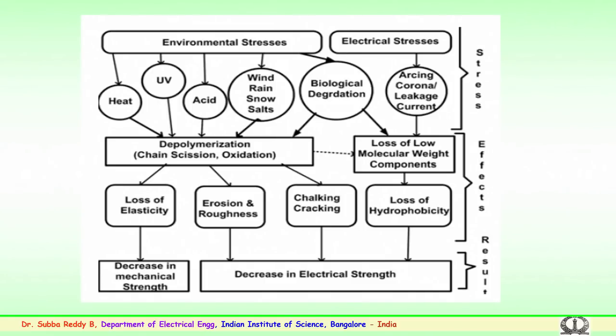This depolymerization could further lead to loss of elasticity, that is, the rubber could become brittle or stiff. This could again lead to mechanical issues, a decrease in the mechanical strength. Further, there is erosion or roughness of the material, or material peeling off from the surface because of continuous discharges or damages, and chalking or cracking because of the stiffness.